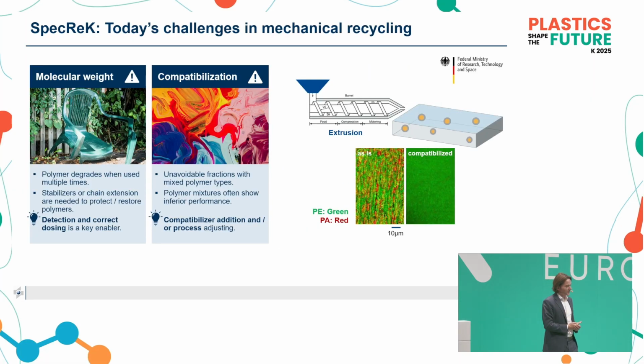So what's the challenge often? First challenge, molecular weight. You degrade the material, reduce the molecular weight, but it's very challenging to measure beforehand. So can Raman spectroscopy measure the molecular weight of the material plus its composition in line? The second one is, often you have polymer mixtures or contaminations in the material. You can take action and add compatibilizers if needed, but you would only do that to a certain level and if really needed. So here again, it's about chemometry, so to measure what's the composition of the product in order to finally end up with steering the process.